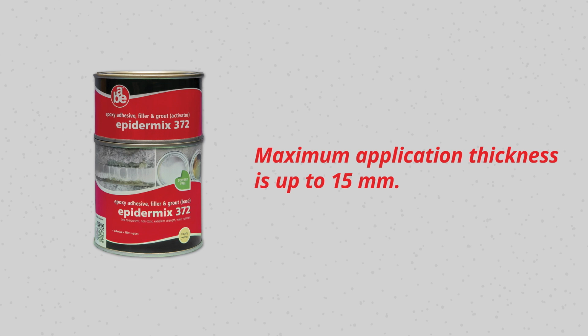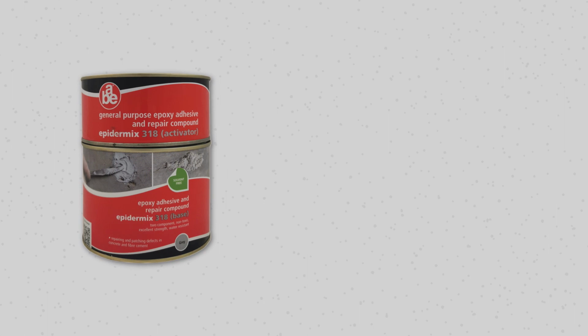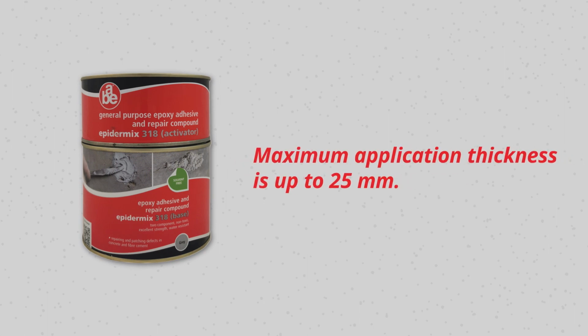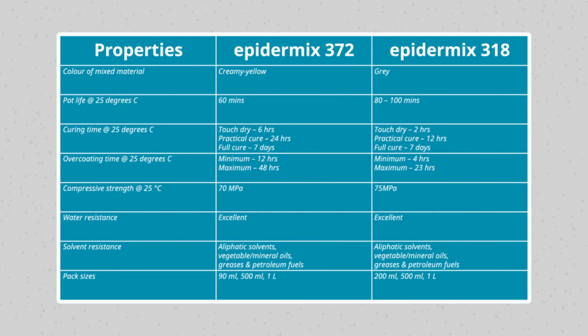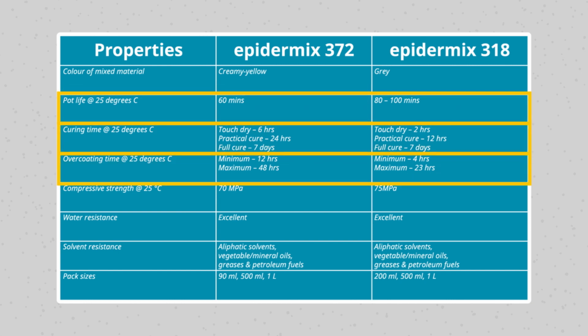For Epidermix 372, the maximum application thickness is up to 15 millimeters. And for Epidermix 318, the maximum application thickness is up to 25 millimeters. It is important to refer to the properties of the mixed material, such as the pot life, the curing time, and the overcoat time.